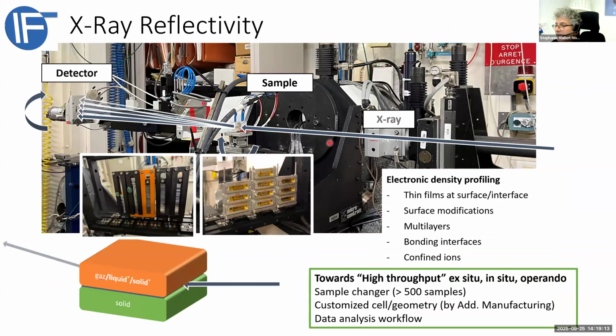First example, this instrument is really well used for reflectivity. And this is quite simple, so we can really cross this dense, or not so dense, material. This technique is able to retrieve the electronic density as a function of the vertical direction. And it is really suited for the study of surface modification, multi-layers, bonding interfaces, and confined ions.